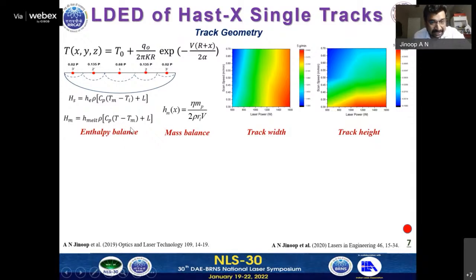The excess enthalpy that is available in the melt pool is used for predicting the track width. At the same time, the excess mass that is available in the melt pool is also used for predicting the track geometry. With this, we predicted the track geometry and it was found to be very close to the experimental values. Then the track geometry variation with respect to the process parameters was studied, and we could see that the track width and track height increase with the laser power, increase with powder feed rate, and increase with the reduction in the scanning speed. The next aspect of the single track is the process window development.